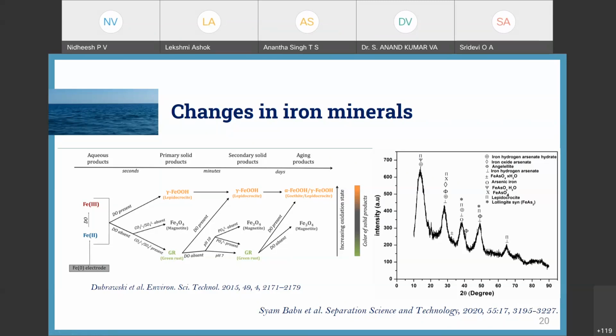I think this is the main reaction, because DO, that means dissolved oxygen, will be very low in the system. For treating arsenic, our target water is groundwater, and in groundwater the DO will definitely be very low. So that's why we are getting very low efficiency, a high passivation rate and magnetite formation. So DO is very important for iron electrocoagulation. This is also our result. We analyzed the sludge and found lepidocrocite, but it contains several other compounds also. It's a mixture of many iron oxides, with some link between iron oxide and arsenate formations in the sludge, and it is purely amorphous. You can see the amorphous nature of this sludge.